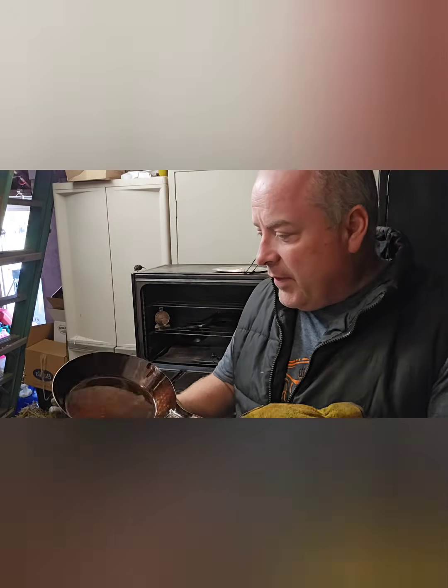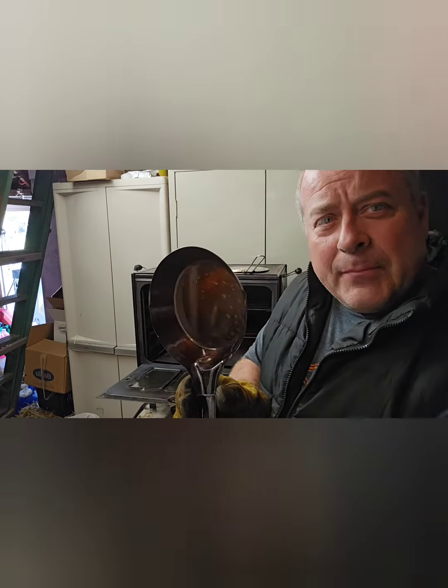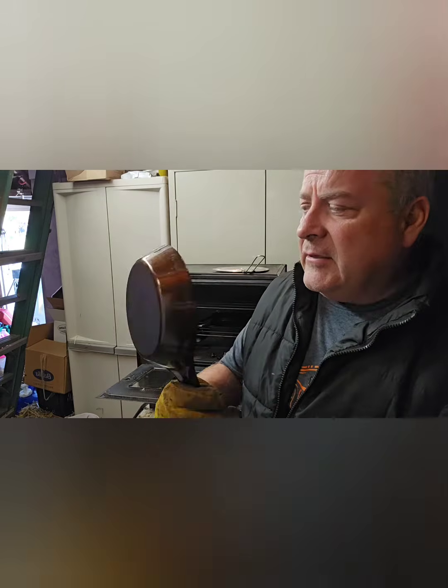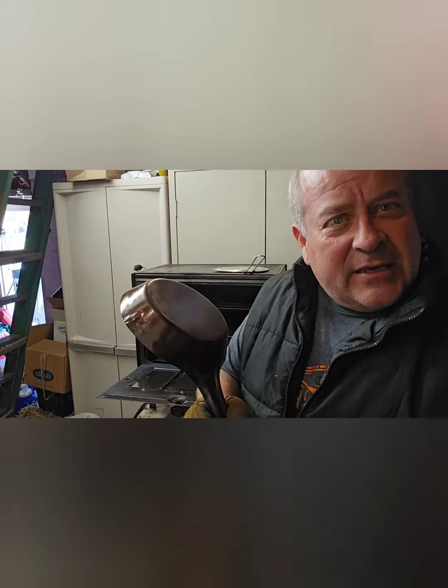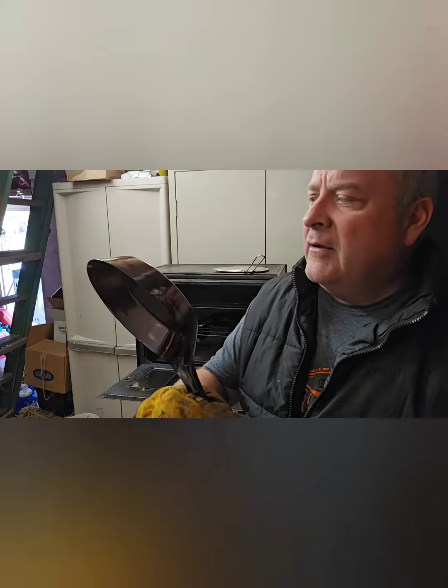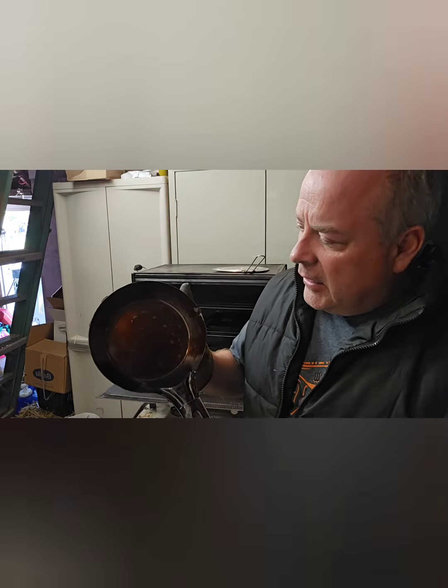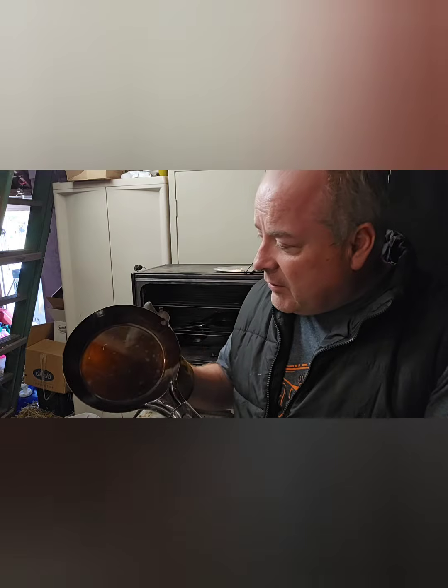It's been about 40 minutes. We're going to pull that pan out. You look at that. You can see the glaze on that pan, and that's exactly what we're looking for. So you can see there's somewhat of an amber color as the steel has heated and that oil has glazed over on the pan and given us an almost gloss non-stick finish, and that's exactly what we're looking for. I'm going to put that back in for just a few minutes.